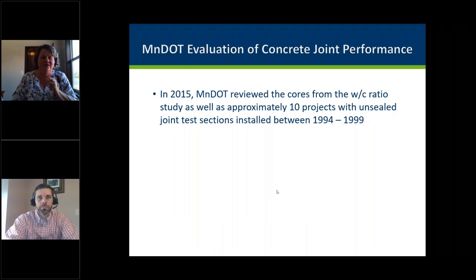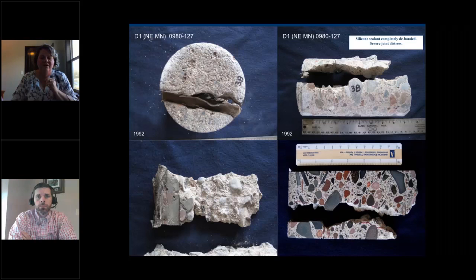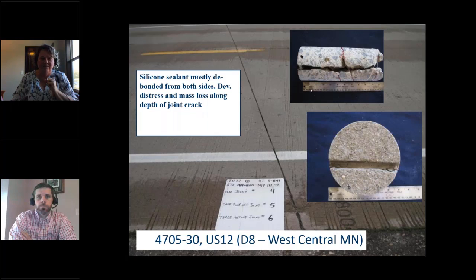So in 2015, we went back and looked at the cores from our water cement study, as well as 10 projects where we had unsealed joint test sections. These are the kind of things that we saw. And so, a picture is worth 1,000 words. This happens to be a pre-water cement pavement with a poorly functioning seal joint, and you can see that the concrete's really taking a hit. Another pavement, this is a pre-water cement. The seal is debonded from both sides, looks pretty good at the surface, but you're starting to see deterioration.